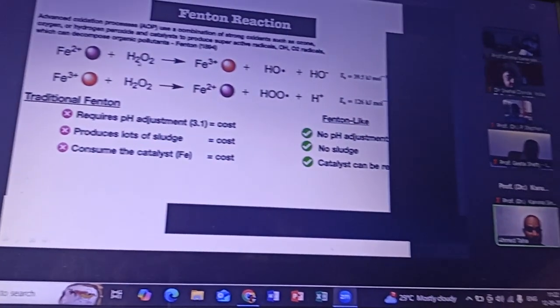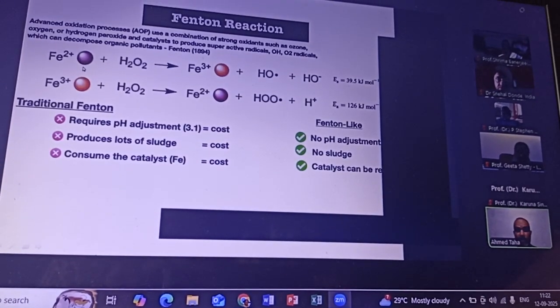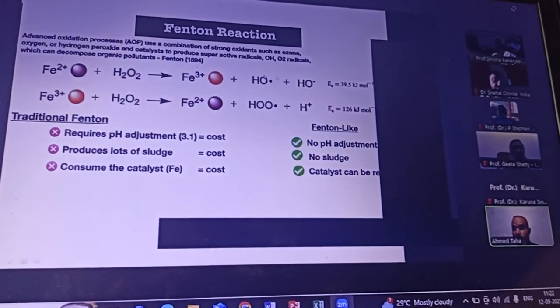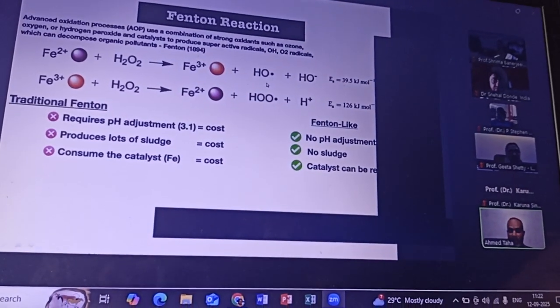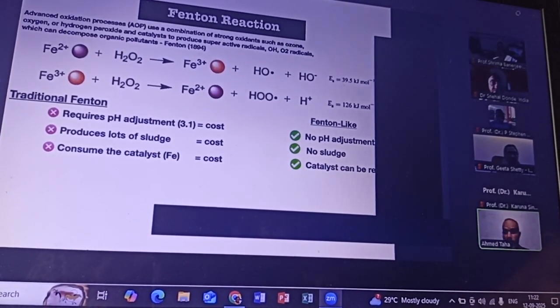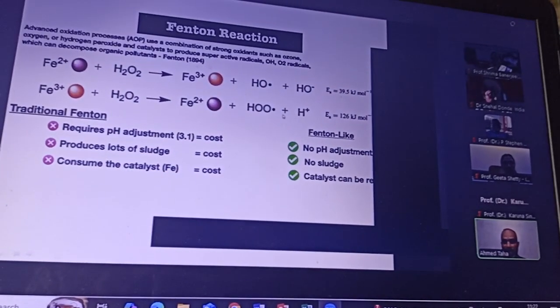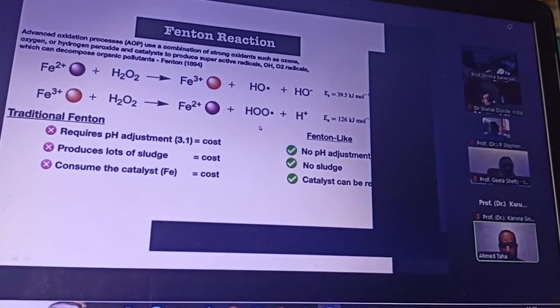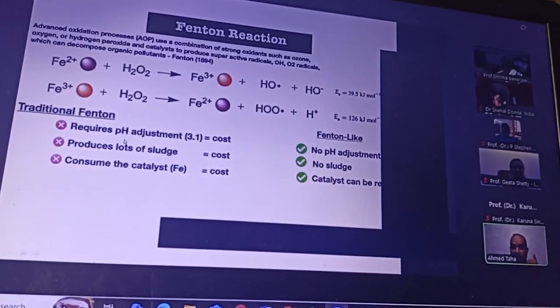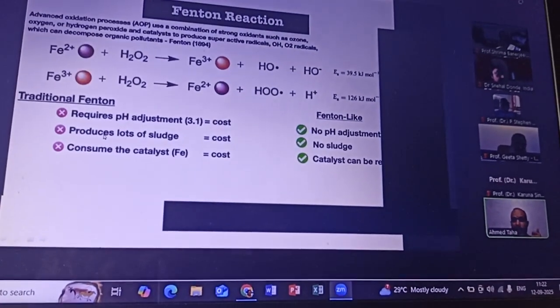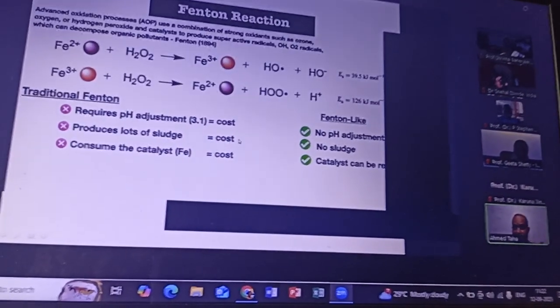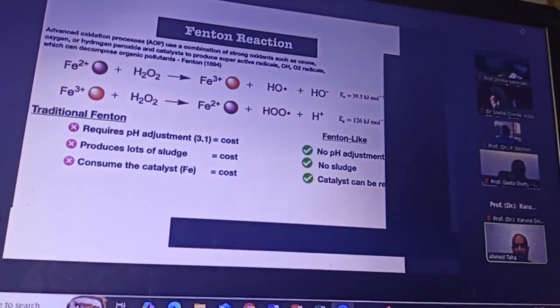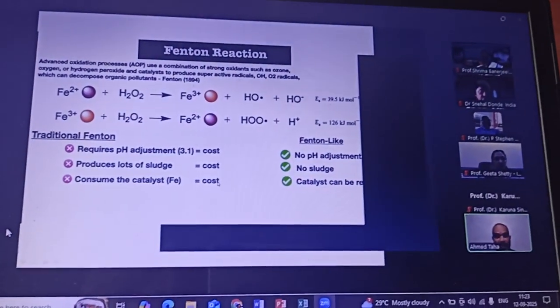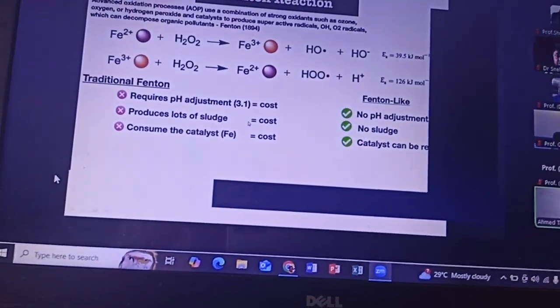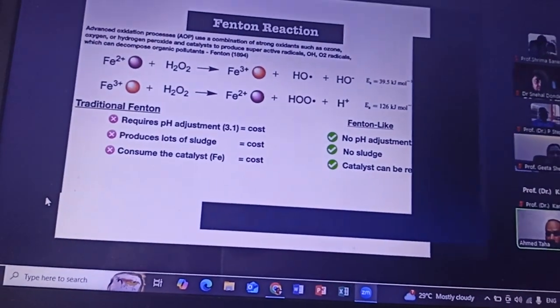So we have the ferrous, and we have an oxidation agent H2O2. When they mix together, this ferrous becomes ferric, and then starts to produce these radicals again. These radicals we have seen before in photocatalysis. This is another way to produce these radicals, and it is a very common technique used in industrial wastewater, but it actually requires a specific pH, 3.1, and produces a lot of sludge, which is a secondary pollutant and costs to deal with. And the catalyst you add is actually consumed, it comes out with the sludge, so you cannot reuse it again. So it's also a cost.